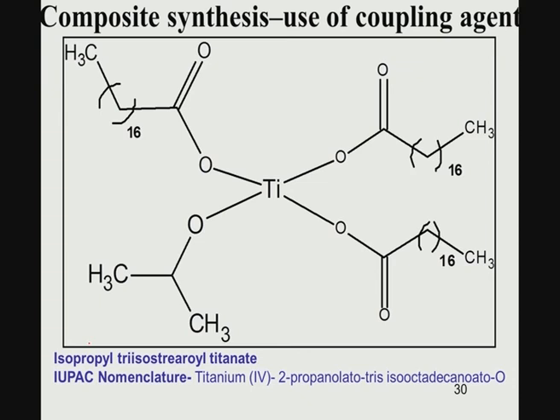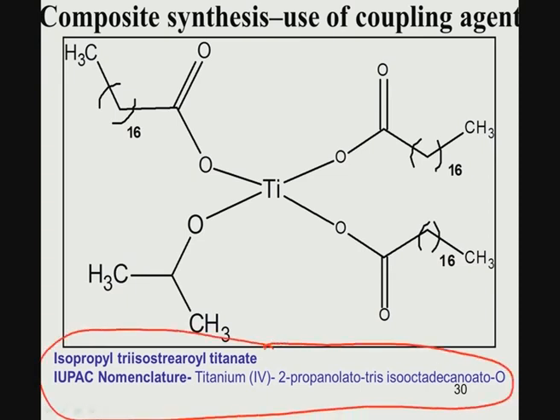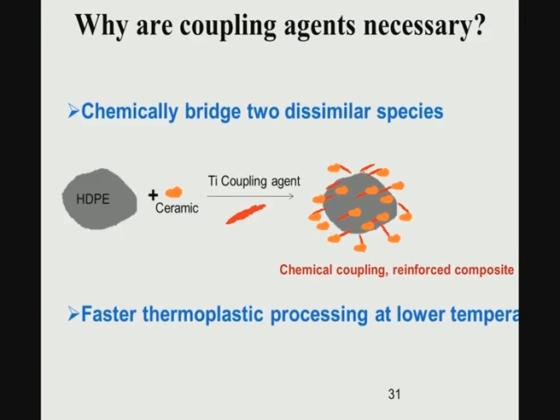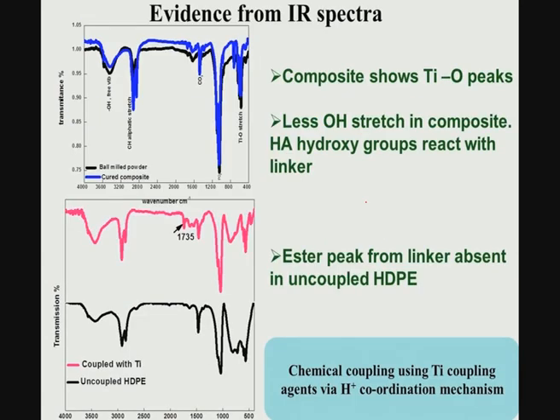Now, earlier I mentioned that a coupling agent needs to be used, and one of the coupling agents that we have used is a titanate based coupling agent with this particular formulation. What you see is titanium in the center, and the chemical composition is very characteristic of this coupling agent. The coupling agent is necessary to chemically bridge two dissimilar species, that is, species which are chemically different. Here you have a titanium coupling agent, high density polyethylene and a ceramic, and you get chemical coupling, that means a reinforced composite, and therefore faster thermoplastic processing can be accomplished.